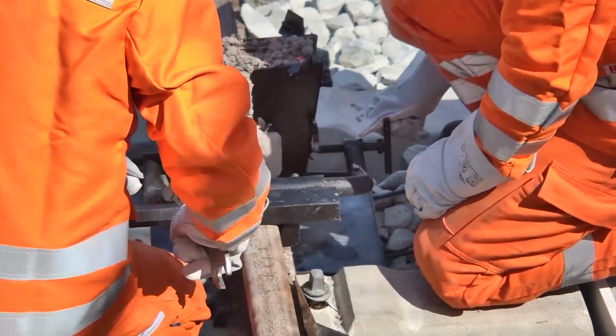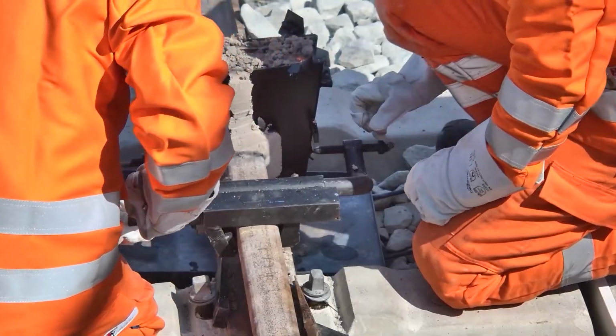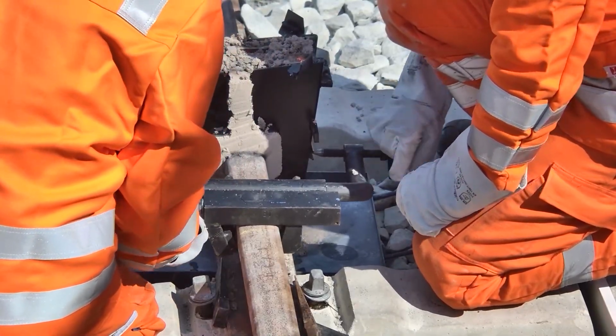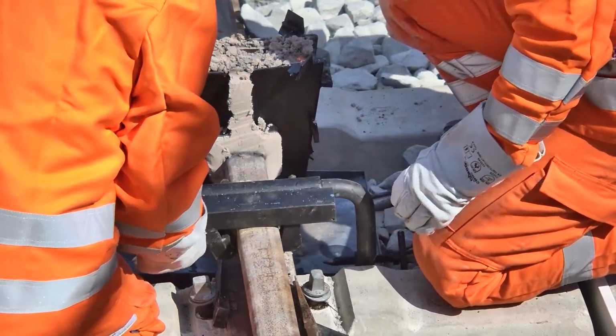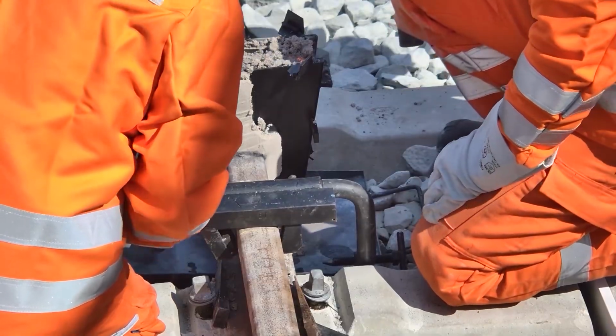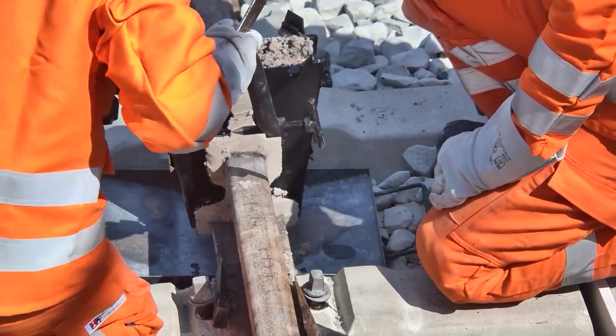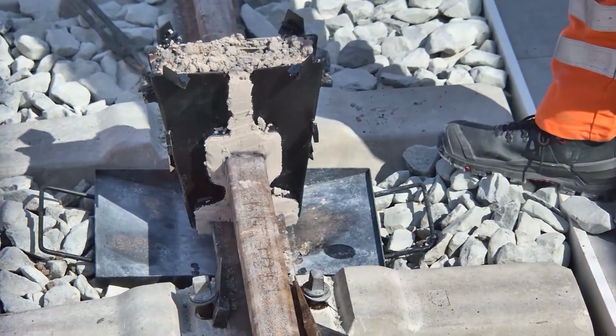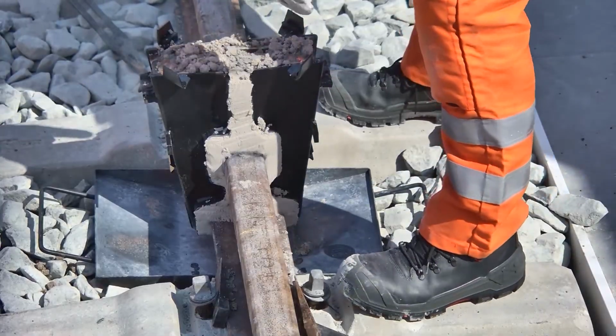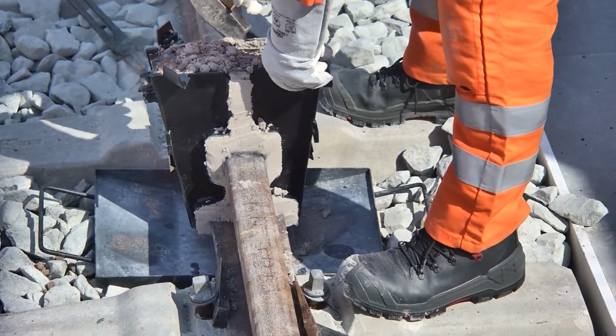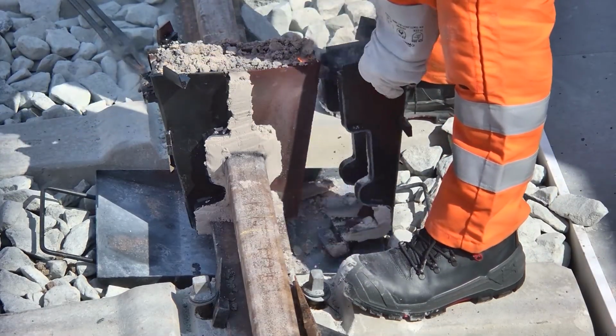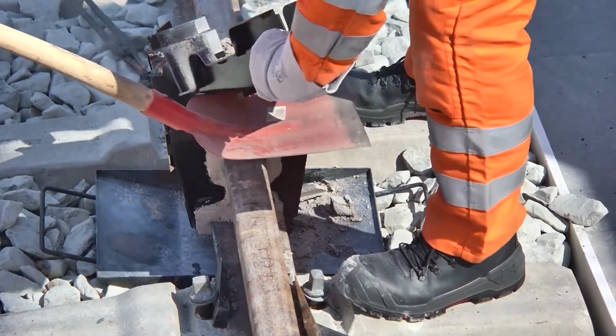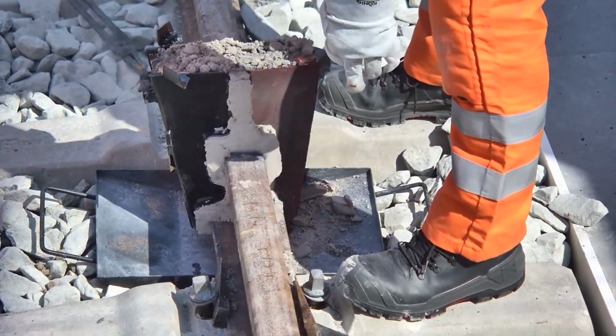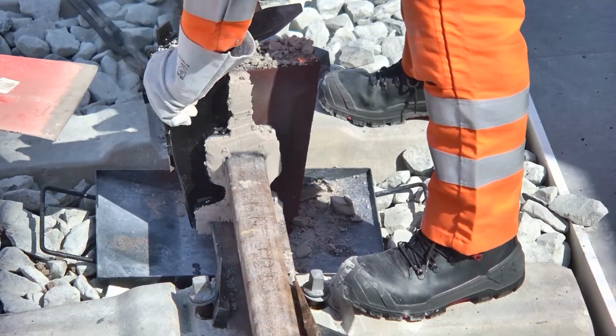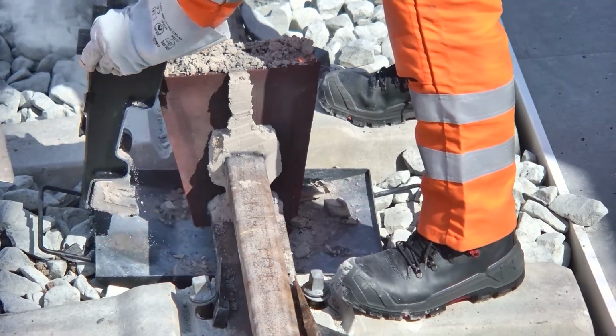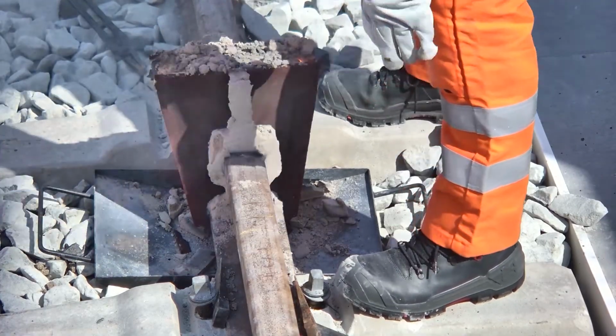After a predefined time, we then take away the mold and shear the weld. So the excess steel that obviously sits on top of the weld and that is necessary to create a robust weld, to make sure that no small deviations in gap sizes or gap shapes or rail shape would actually create problems. We always have excess steel, and that excess steel needs to be taken away now.